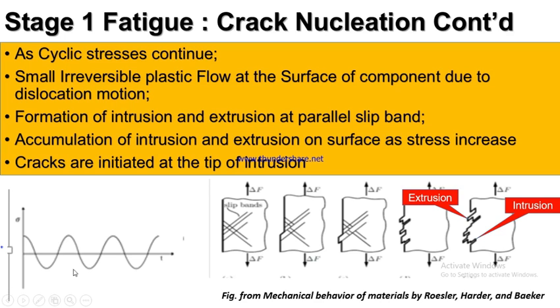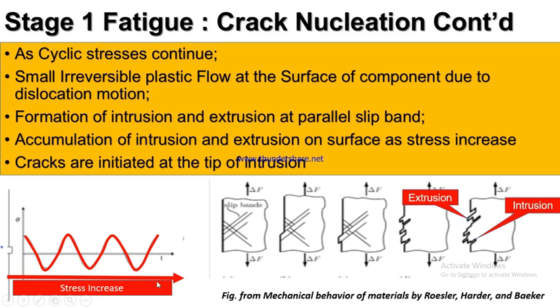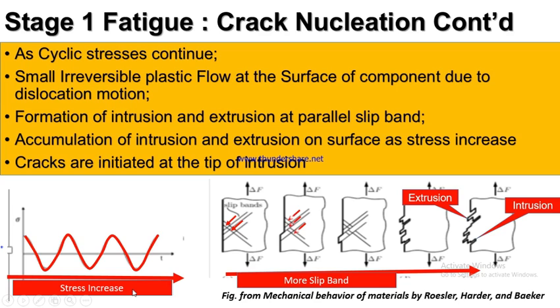When these dynamic loads take place over a long period of time, microplasticity starts to take place. This microplasticity will definitely lead to slip occurring at the surface, which will make the material change, as you can see here. As the stress increases, we will have more slip bands incorporated into the system. These are the slip bands, you can see them here. As you continue to increase the stresses over a long period of time, more slip bands form, and by so doing you begin to see that there will be a surface discontinuity.